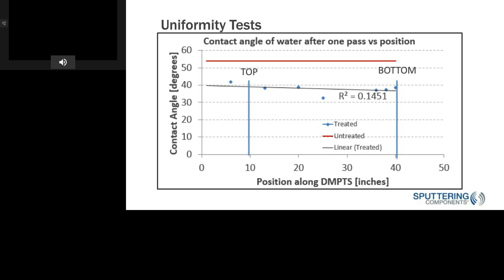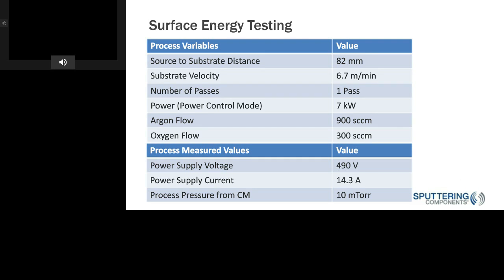Then we looked at surface energy testing. So these are the parameters that we use. The source to substrate distance was around 82 millimeters. The substrate velocity 6.7 meters a minute. We just did one pass, and I mentioned that higher power for the short duty cycle. The argon flow was 900 SCCM and oxygen 300 SCCM. Power supply voltage 490 volts, and the current 14.3 amps with a pressure of 10 millitorr.